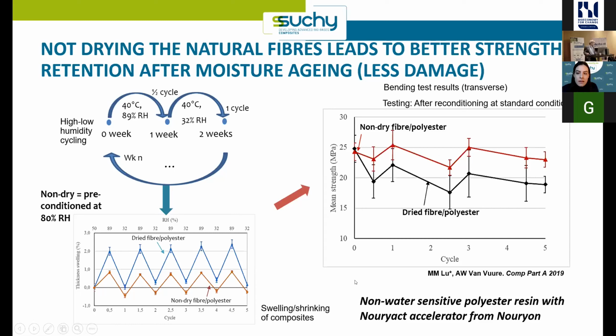Of course, you can only do this when your resin can stand the moisture in the fiber, and also when during the processing, you don't create steam and porosities and so on. So of course, you have to look for all these boundary conditions. And especially in the case of polyester resin, you need a not water-sensitive polyester, which means a not water-sensitive accelerator. And that is what Gea Spijkerman will soon talk about after my presentation. They developed a non-cobalt, so environmentally friendly accelerator, which is also not sensitive to water, which allows you to do the very thing I'm presenting here.